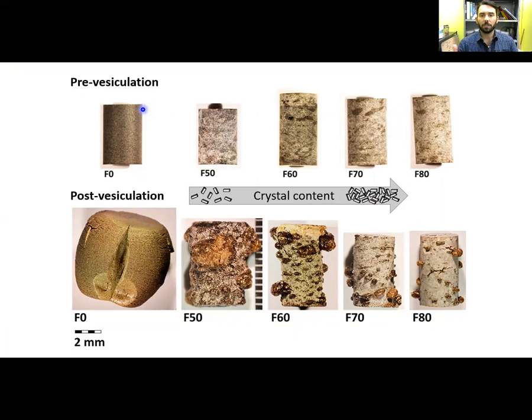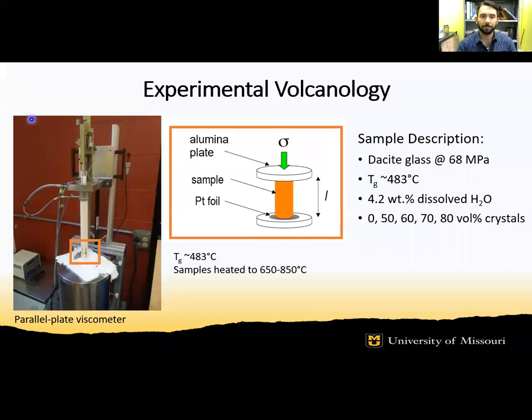The goal of this project was to experimentally vesiculate hydrous dacitic melts with varying crystal contents. We then measured the subsequent bubble-driven inflation of the sample, shown here to scale, as a means of identifying the onset of permeable outgassing. In order to simulate decompression-driven vesiculation, our dacite samples were quenched at a final pressure of 68 MPa with 4.2 wt.% dissolved H2O to simulate a shallow reservoir.